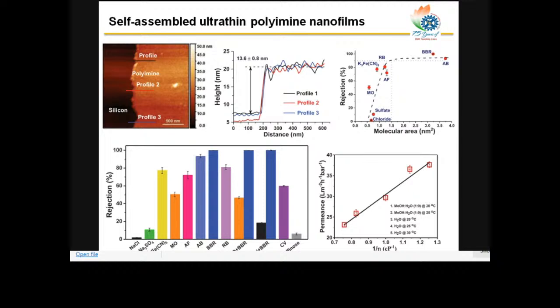Then we actually got an oligomer of the polyimine nanofilm first. So this oligomer will get self-assembled at the interface on top of a water surface, basically. And it will form a very thin, like around 13 nanometer thin film. At this 13 nanometer thin film, as you see in the AFM, we got the similar measurement like I explained in the last example. From the step height, we can measure the thickness of the polymer thin film.